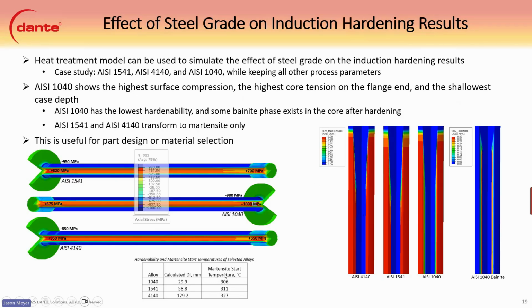1040 does have the lowest hardenability. You can see here the DI is only about 30 millimeters. And we do see some bainite phase during quenching or after quenching in the core. Whereas the 1541 and the 4140 transform to martensite only in the case. And this is really useful in part design and material selection. So if you wanted to test different materials, you can look at it and see what kind of response would happen with the same heat treatment schedule that you would use.